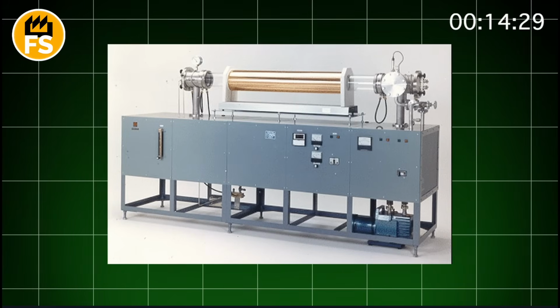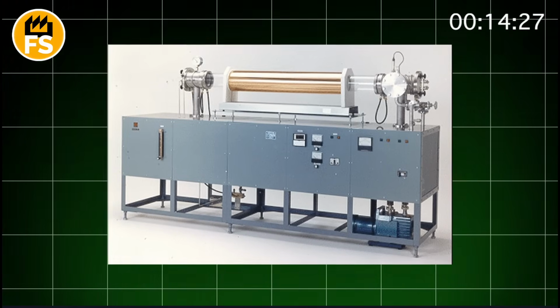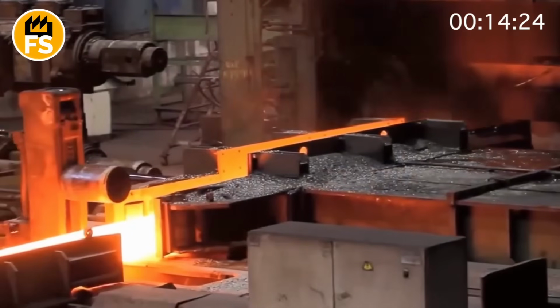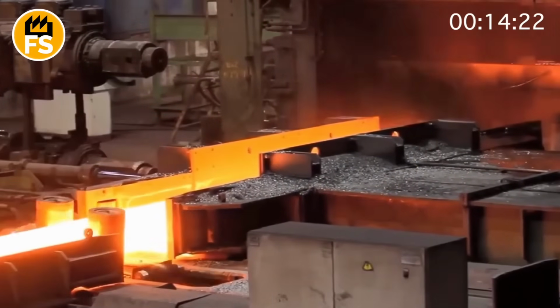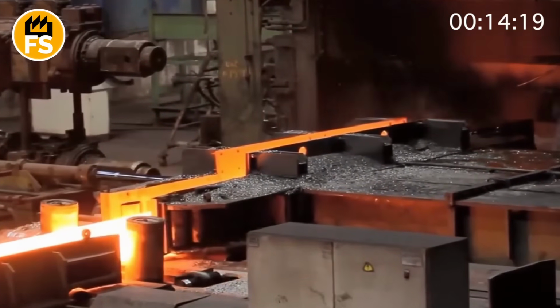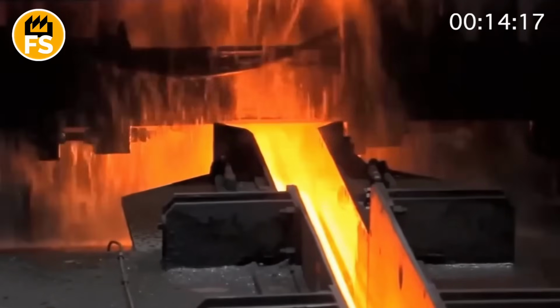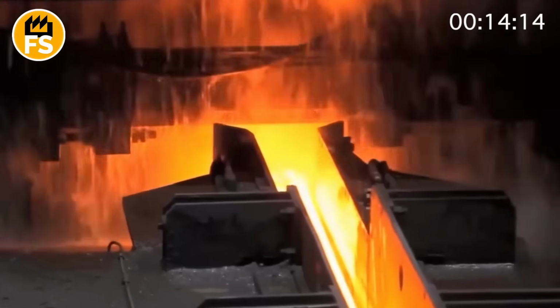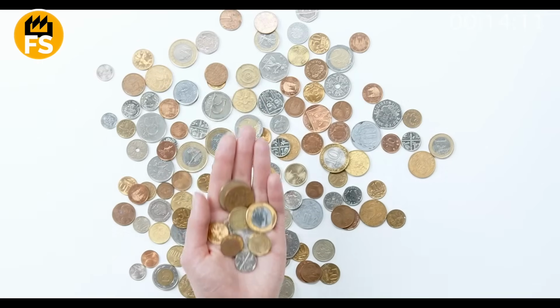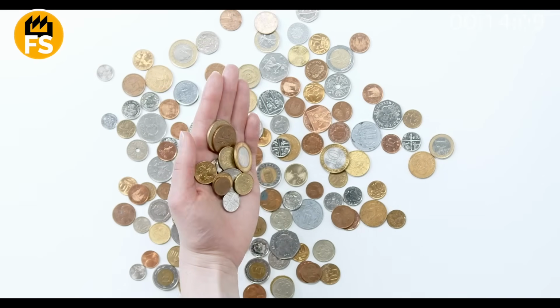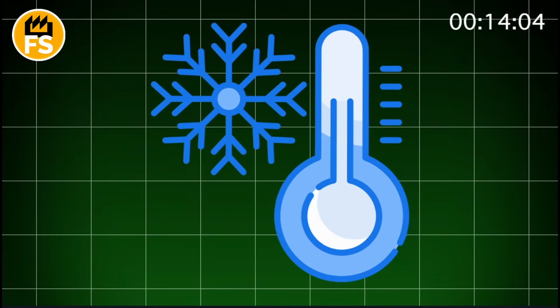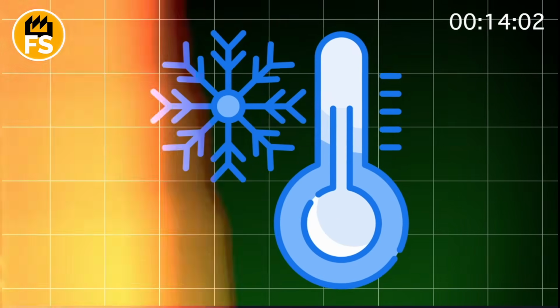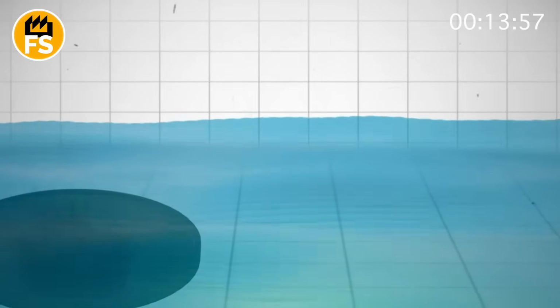Next, a real fire ritual, the annealing furnace. These metal circles race through a long furnace, 12 to 40 feet long, where the temperature reaches a crazy 1,250 degrees Fahrenheit. The metal becomes red hot, but doesn't melt. It softens. It's like warming up the body before hard work, so you don't tear a muscle. After the furnace comes rapid cooling. The circles fall into a bath of cold water, about 50 degrees Fahrenheit. This temperature shock makes the metal stronger and more elastic.